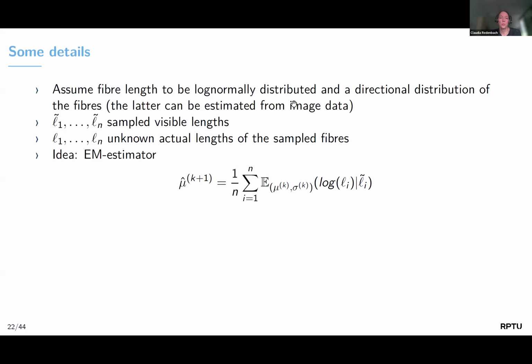And then if we want to estimate the parameters, for instance, if we wanted to estimate the mean of the logs, then the idea would be to take a sample mean of the expected log of the actual length given the observed length, because that's the only thing that we have. How do we do that? We would need the distribution of L given L tilde. Well, we could use Bayes' law to say, that's the distribution of L tilde given L times P of L over P of L tilde. And the things on the right-hand side are known.